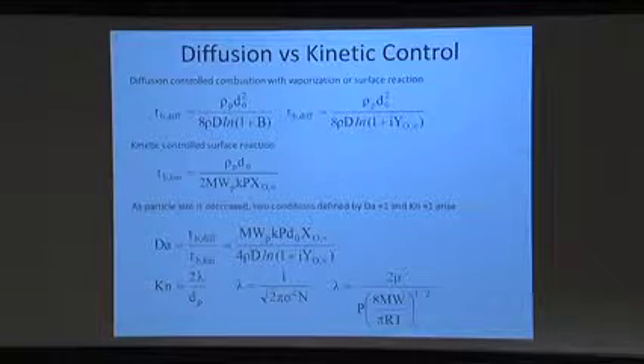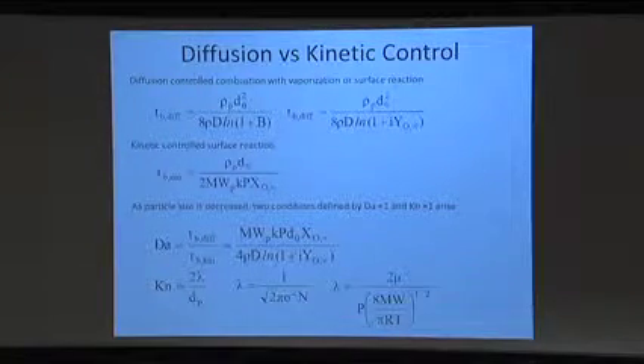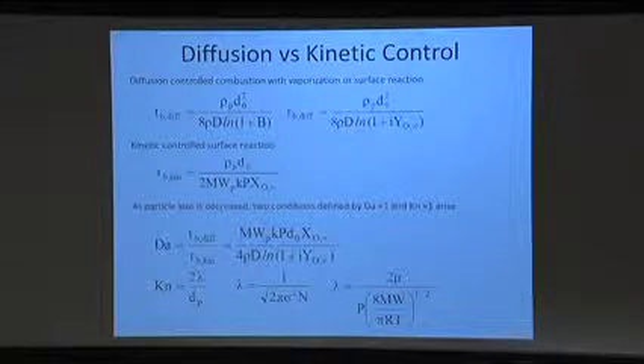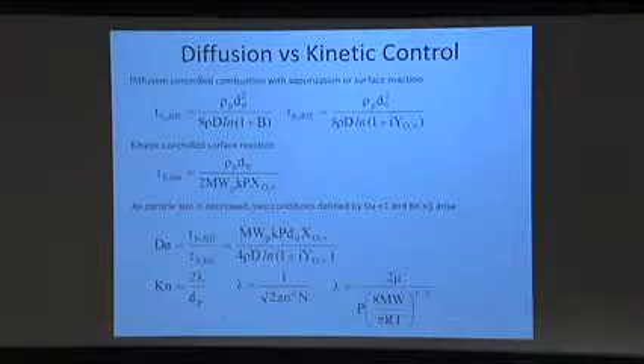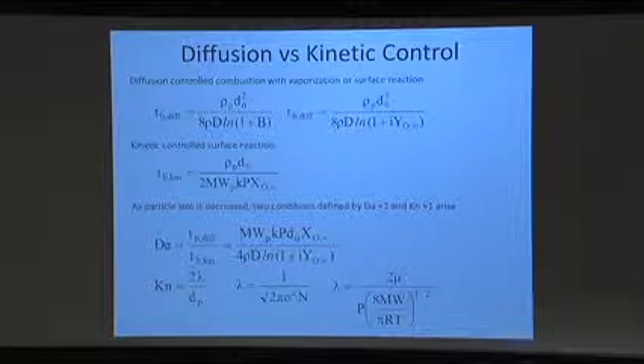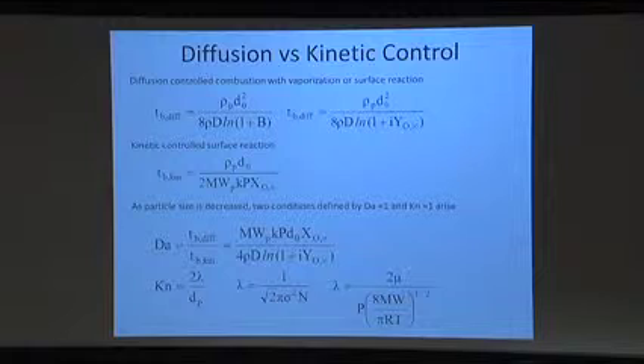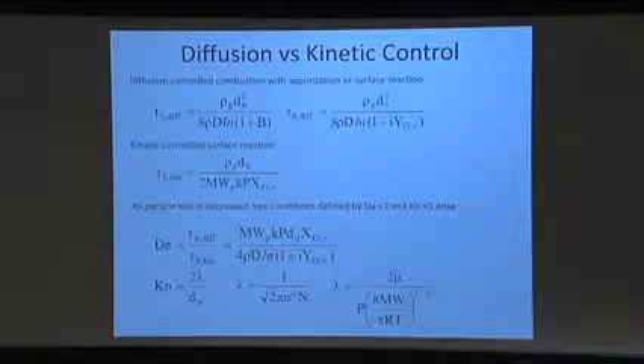There's another important time scale that comes involved here, and this is essentially looking at the Knudsen number, which is a comparison of the particle diameter compared to the mean free path of the molecules in the surrounding gas. And when these become of the same order, what that means is that now I'm leaving essentially this continuum where I'm assuming the particle has much larger dimensions than the spacing of the molecules and the collisions are frequent. But now I'm coming down into a free molecular regime when they're of the same order here.